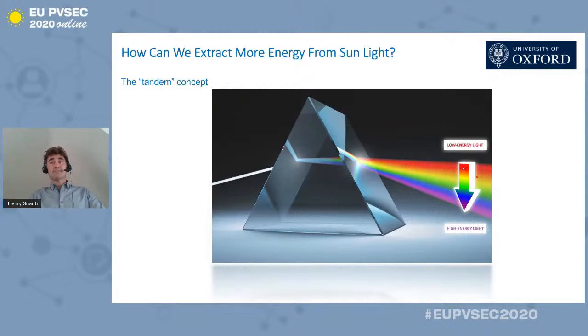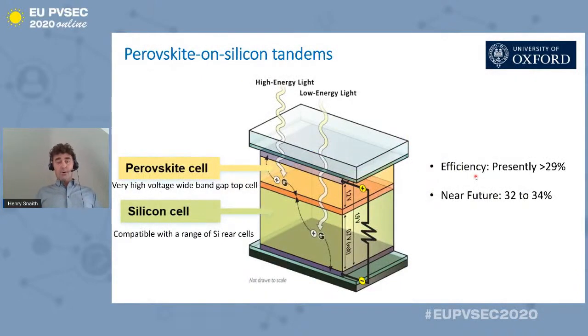So if you can slice this spectrum up, capture it in different solar absorbers with different bands of absorption or different band gaps, then you can stack them on top of each other and extract a lot more power from the solar energy. So that's precisely what we do with perovskites. We put perovskite on silicon, and at the moment, the best recorded cells are at over 29% efficiency, which is already pretty outstanding. But actually, in the near future, we estimate that we should be able to push this up to between 32 to 34% without doing anything fundamentally different, just more optimization, solving problems we know we have.